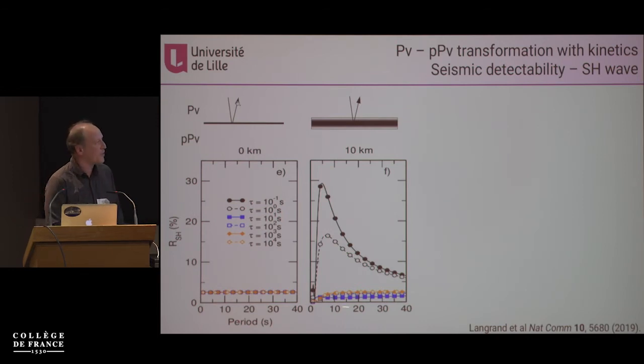So here is the wave period, and the reflection coefficient for S waves. And so you get an amplification, and it depends on the time scale of the kinetics for the transformation. So if you have 1 second kinetics, your reflection coefficient can increase dramatically.